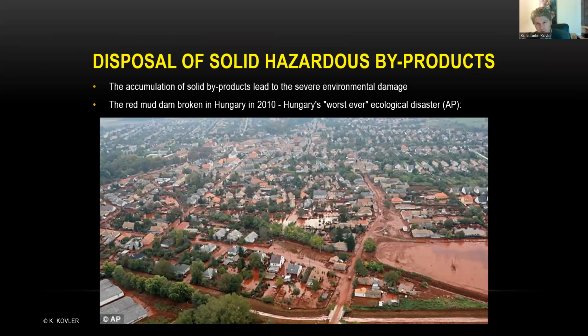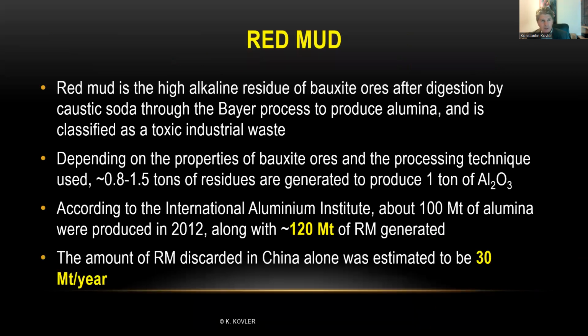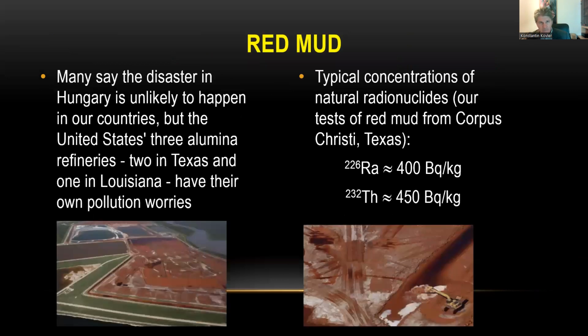Disposal of these solid hazardous byproducts can lead to severe environmental damage, like what happened in Hungary in 2010, the worst ever ecological disaster, when a huge territory of Hungary was simply flooded by this toxic byproduct. Red mud is a highly alkaline residue of the bauxite industry. And look at the numbers. Only in China, the amount of red mud discarded is estimated to be more than 30 megatons per year.